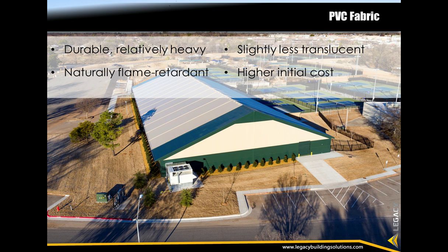PVC fabric has a higher tear strength than PE fabric and is designed to last longer, often up to 30 years. All PVC fabric is flame retardant. The disadvantages of PVC fabric are that it has a relatively higher initial cost and is generally less translucent.